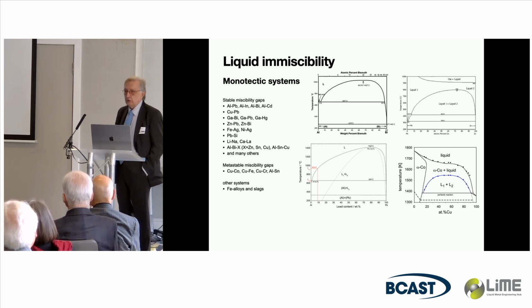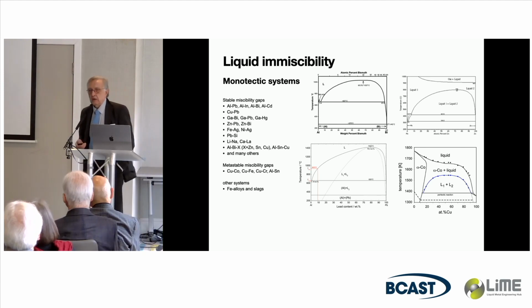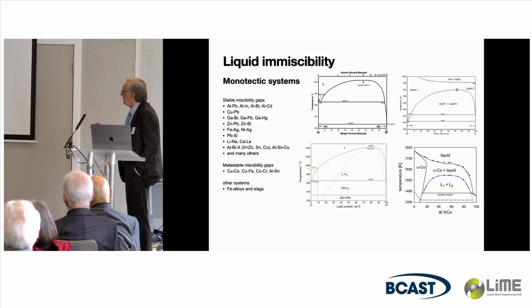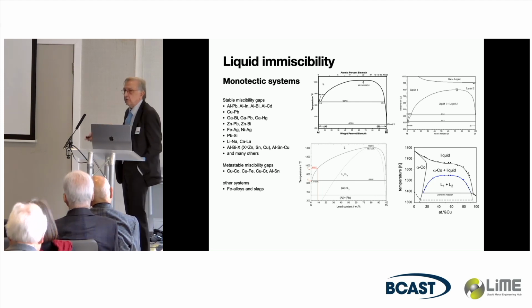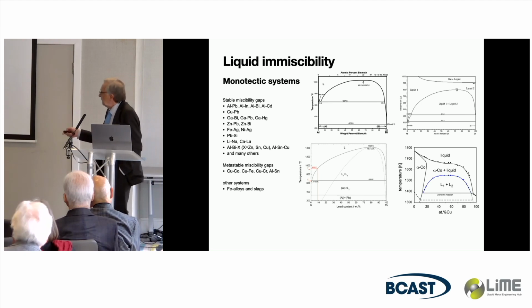cool it, and if you do it nicely, and Dieter Herlach did a lot of research on that, and his co-workers still do a lot of research on that, and you are able to suppress the crystallization of, let's say, cobalt, and you can go directly into the miscibility gap, and so you see a wonderful two-phase structure.